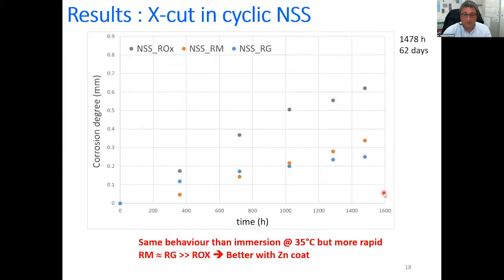If now we look at the result with the X-cut panel in cyclic neutral salt spray, again we find that the ROX system is the worst one, but with RG and RM systems, it is not possible to differentiate between these two systems. The RM and RG are better than the ROX system, so again it is better with the zinc coat, but we cannot differentiate the two systems. And one thing which is also important is that this test in neutral salt spray is more rapid than the previous one in a solution at 35 degrees C.